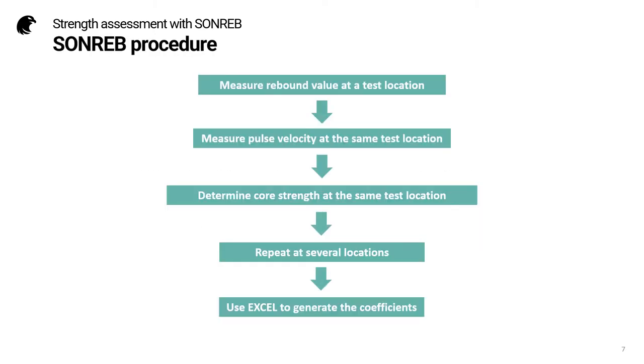And here we can see the SONREB procedure. We measure the rebound value at a test location. We measure the pulse velocity at the same test location. Then we determine the core strength at the same test location. We repeat this at sufficient locations and then use Excel to generate the coefficients.